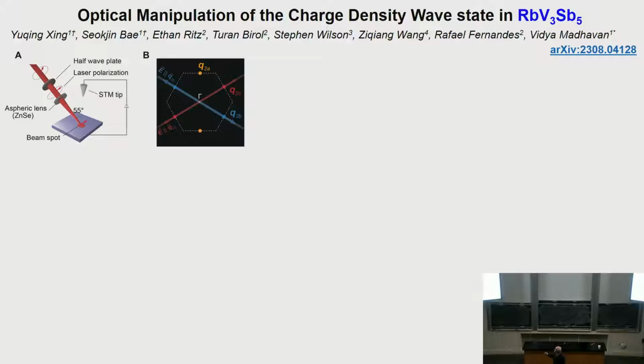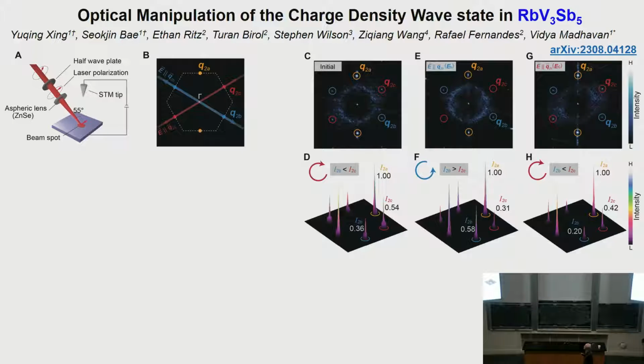So this light comes in, and the polarization direction of the light she can control. That polarization can be along one of these crystal axes, these two directions, where you see these peaks are of different height. You can ask, what about this one? She's going to avoid this because this material, rubidium vanadium antimony, has stripe ordering along this direction. So this direction is already very special. Let's leave that out. But she's going to probe these two directions. So this is what her experiment showed.